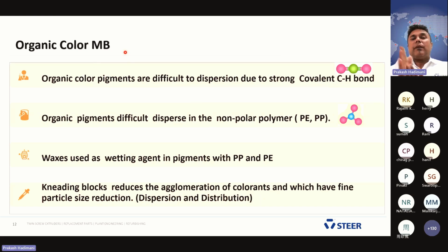Now we are talking about organic dry powder pigments. Why are dry organic pigments difficult to disperse? Yes, there is a chemical structure and the phenomena. Organic color pigments are difficult to disperse due to strong covalent bonds in the pigments, carbon and hydrogen. When you break this bond, you need to apply high shear. You need to apply high energy to break the bond. That is why it's difficult to disperse organic pigments.